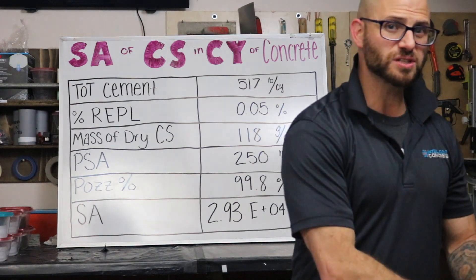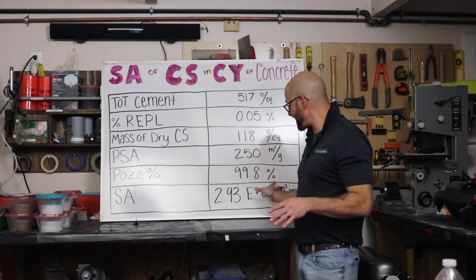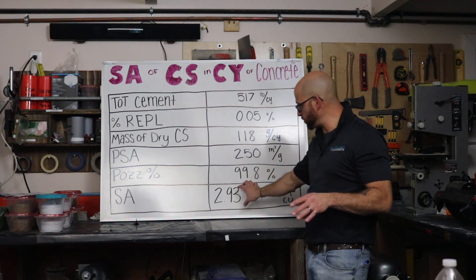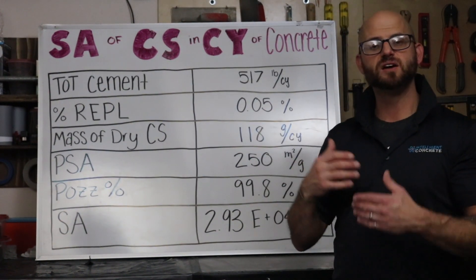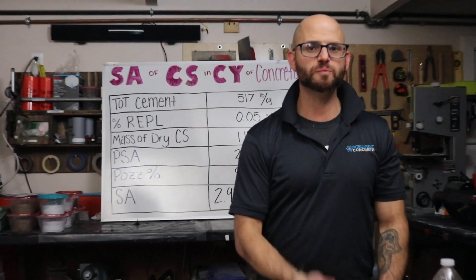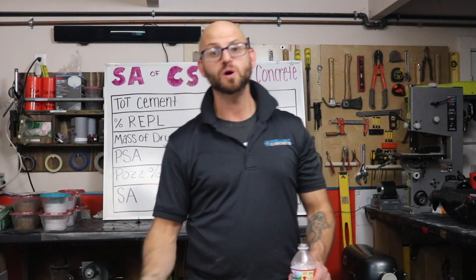What we would normally do is calculate that same value for silica fume or fly ash, use that pozzolanic surface area, feed it into our system, and back-calculate how much dry colloidal silica we would need. From there we also calculate fluid ounces per hundredweight to get the colloidal silica dispersion into the back of the truck — or milliliters per kilogram of cementitious for batch computer input. If we don't cover that conversion here, we'll do another video on it.